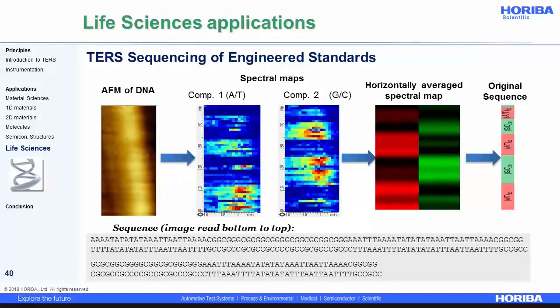Plotting this spatial distribution shows a very good correlation with the structure of the DNA. You have the DNA test sequence shown on the bottom of the slide. And this very good correlation with the original sequence is obtained with only minor disturbances caused by the drift of the sample, which is almost inevitable at this scale. Here I'm talking about the horizontal lines that we can see on the average TERS map. The authors of this work also showed DNA sequencing with a resolution down to 3 to 4 bases.